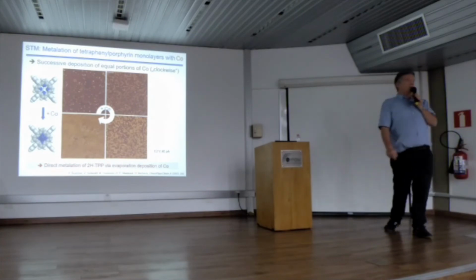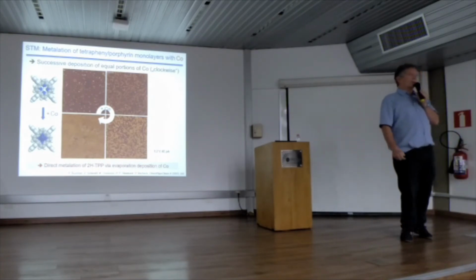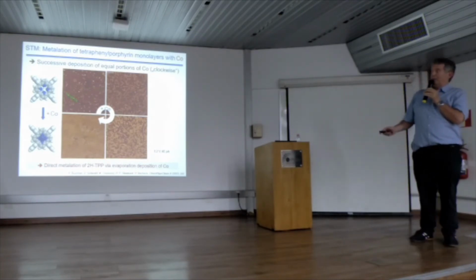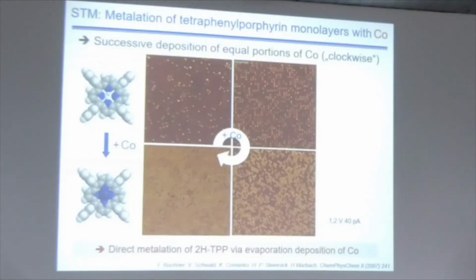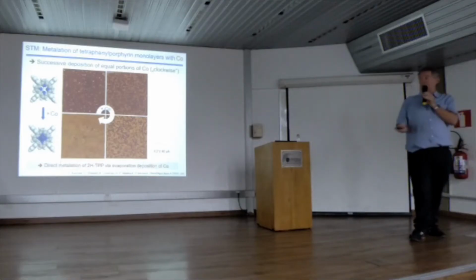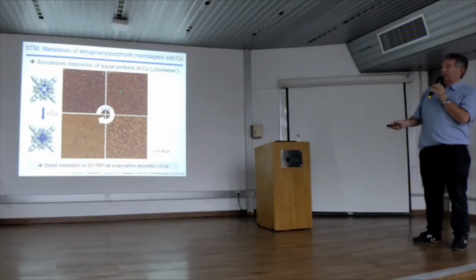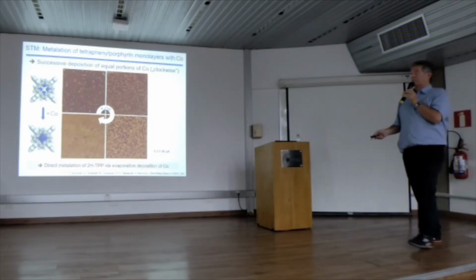Some people don't believe in XPS. You would not imagine, but this is the case. So we also did STM, and I also showed you some STM images here. So here you see, you increase the amount of cobalt, and you have a chemical contrast between the species. The free base is dark, and the cobalt is light, bright.